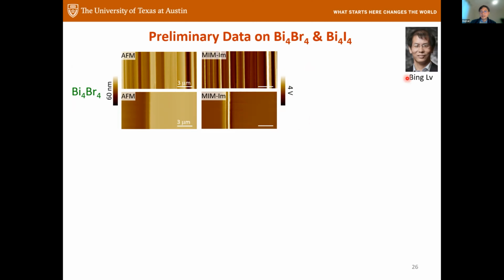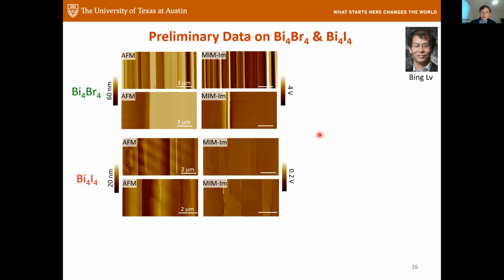And interestingly, right, so Bing also gave us some iodine sample. For the iodine sample, if you compare the scale, this is hundreds of millivolts, and sometimes even this is, for those of you who used to look at this false color scale, they're only about here. So for the iodine samples, the signals are much weaker, and we never see volts-like bright lines.